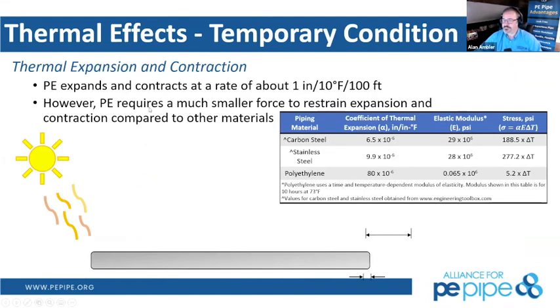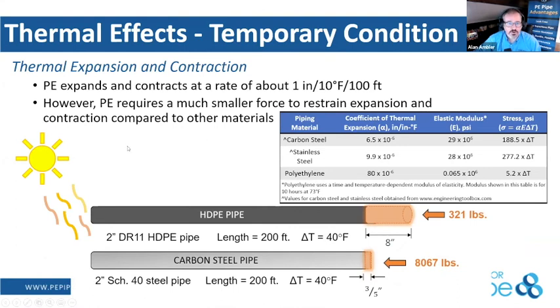I appreciate it. So again, this concept of movement along the thermal expansion or Poisson's effect, I really wanted to hit home, and this explains why high-density polyethylene is a monolithic system and self-restrained. So even though this temperature change of 40 degrees Fahrenheit above ground would change the length of the high density polyethylene 8 inches versus a carbon steel pipe only 3/5 of an inch, the actual force required to restrain that is significantly less.